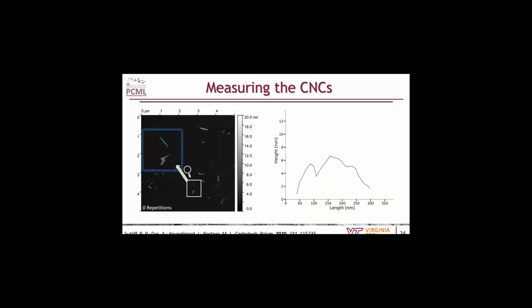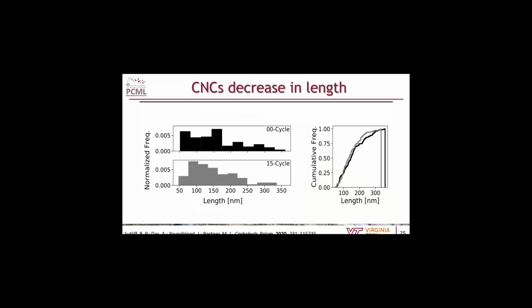Do this a couple hundred times for each sample, and you can build histograms. In this case, we have our 0 cycle on top and our 15 cycle on the bottom. We start out with a pretty decent population of 300 to 350 nanometer nanocrystals, but after just 15 repeats, 35 milliseconds, we start to lose all of our 350 nanometers, see a decrease in our 300 and 250 nanometer samples, and start to see a rise lower down around the 100 to 150 nanometer range. So it's quite likely we are snapping these guys in half.